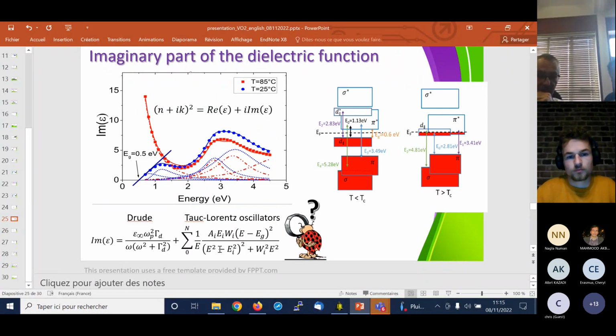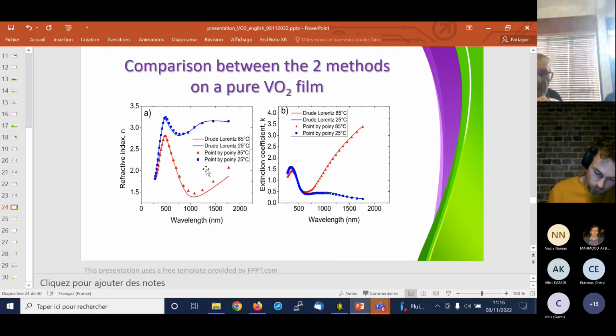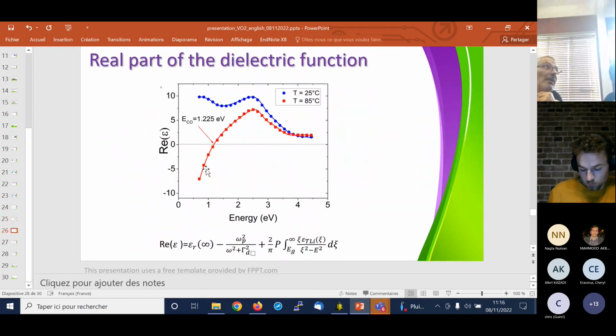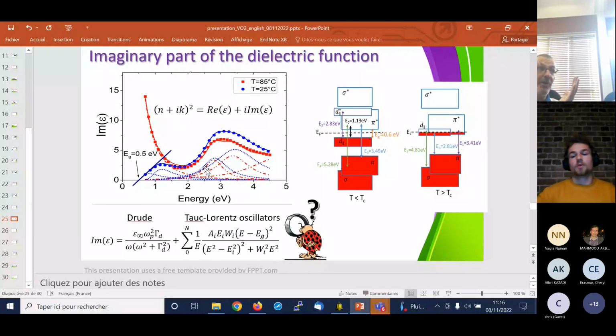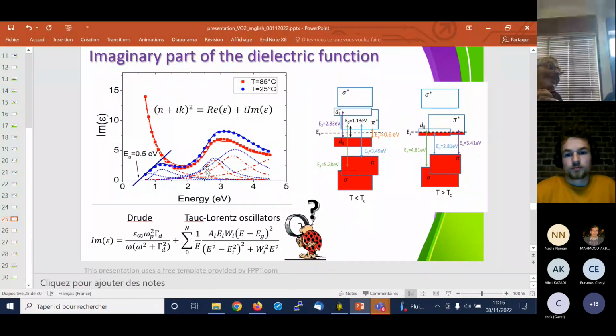In some cases, you can see here that the Tauc-Lorentz does not describe this part extremely well, because the Lorentz shape is quite extended, and you could use a Tauc-Gauss oscillator, but with the Tauc-Gauss oscillator, you cannot calculate the real part in an analytical way. So this is why we use the Tauc-Lorentz oscillators. But for the Tauc-Gauss, there is no analytical expression for the real part of the dielectric function. So I hope that I was answering your question.